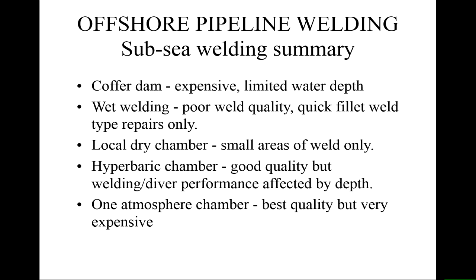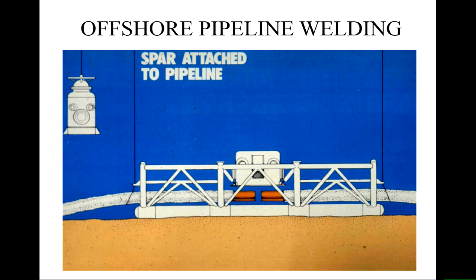If you really have to weld and repair something that's sitting on the seabed and you're in tens to hundreds of meters depth, then you might want to have a chamber where you pump out the water, but you still have the pressure head. That's what they call a hyperbaric chamber. You can get good quality welds from that, but then you have to weld under high pressure conditions, and that's very hard, particularly on the welders. So you have to have good quality and welder performance assessments. And the welders have to be divers as well to do that, which is not always straightforward. And then finally you get a 1 atmosphere chamber, which is a very expensive way of doing the weld, but you can use the standard welding procedures for doing that. There are other things you could do.